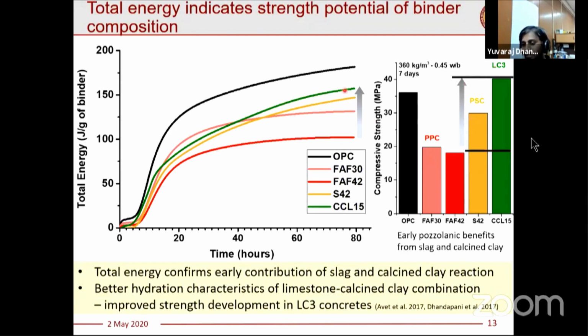And you have calcined clay limestone cement, which is the LC3 combination, for which a current composite cement standard is under progress, which will eventually come out in due time. So the early pozzolanic reaction with these two SCMs starts impacting the property from a very early age. And by using a combination of these SCMs, you can improve the properties of your concrete systems right from a very early period.